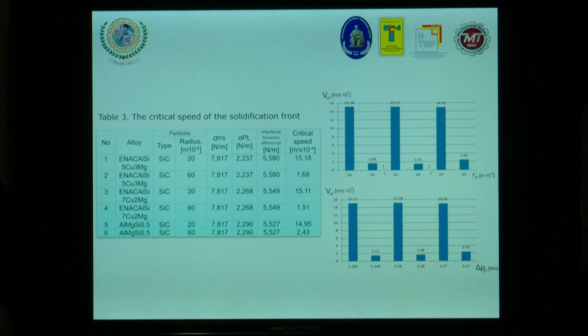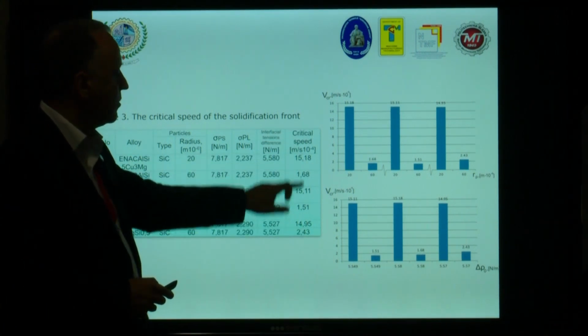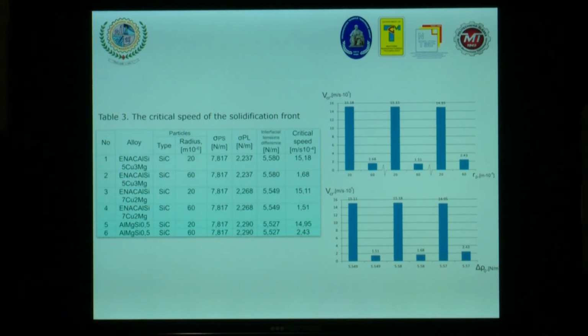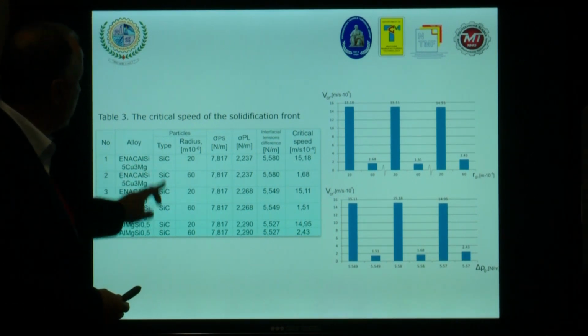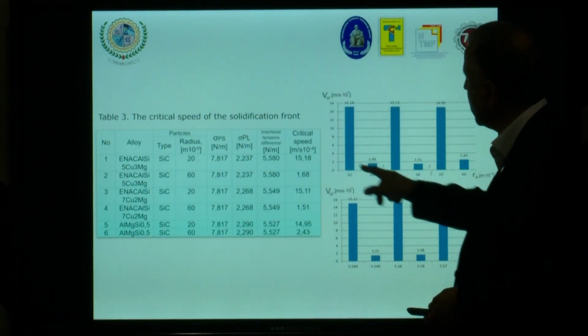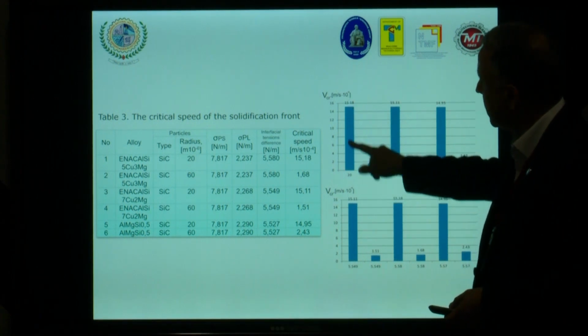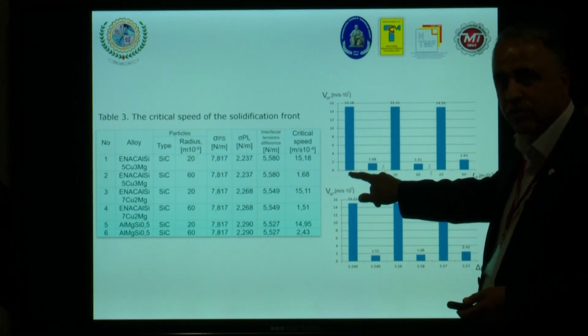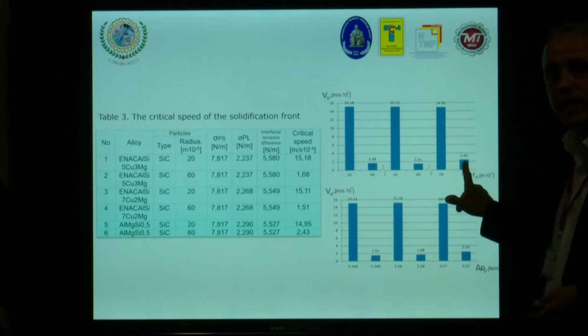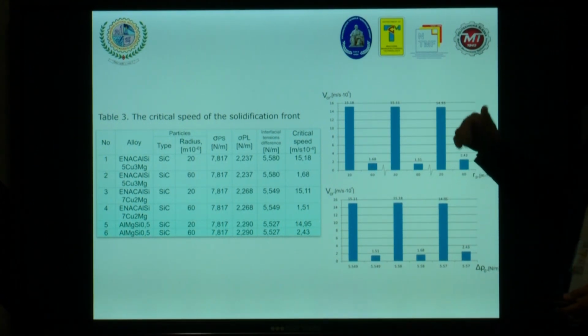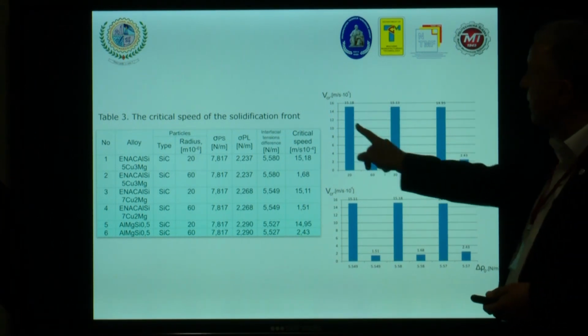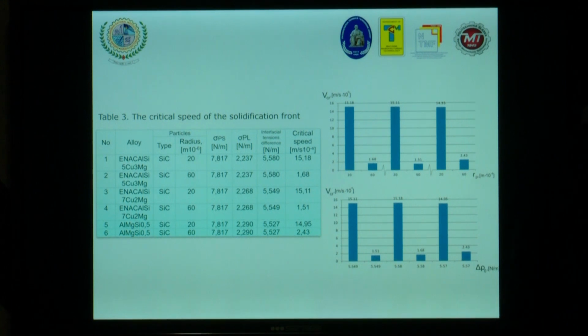Now the critical speed of the solidification front. I put here the information, also taking into account the critical speed values calculated from liquid to solid, because now we are talking about the solidification front. And also, you can see the type of the particle, radius, interfacial tension difference, and look here about the variation, what happened with the smallest radius, what happened with the highest radius of the particle. So we can talk about the highest speed only in case of the small radius of the particle used.